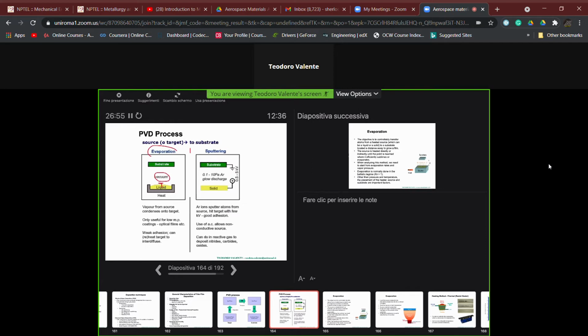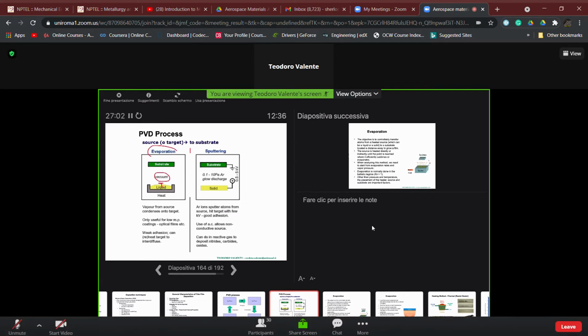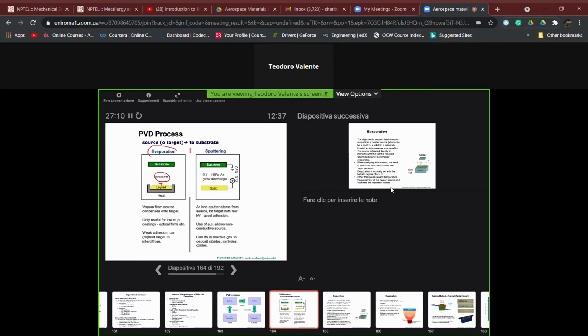This means that all the system of the pumping unit for the PVD, and it's another reason of cost, is more performing than those which are used in plasma or thermal spray based technology. And one possibility for the thermal evaporation is, for example, to put heat on our target. So we have called it target, that is the source material. And due to the presence of vacuum in the chamber, the vapor pressure, that is the evaporation of this solid phase, generates the gas, which will then be deposited by condensation on the substrate. This system, the standard, the most simple, if you want, system to get evaporation by thermal effects, is